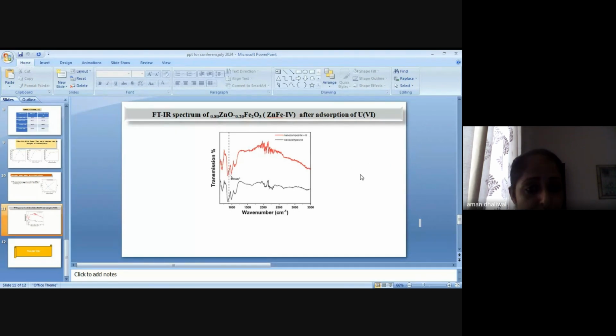This is the IR spectra that was taken before and after the uranium was adsorbed. This one is the IR peak before the uranium was adsorbed, and this one is after the uranium was adsorbed. And at 910 centimeter inverse, a characteristic peak was observed. That corresponds to the uranium adhering to the surface of these adsorbents.